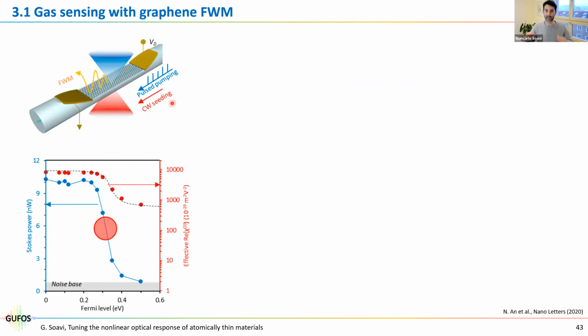So now we take a fiber, we remove the top part, and we make what we call a D-shaped fiber. By doing that, we will be very close to the core of the fiber. We now place graphene on top of it in a way that light that propagates inside the fiber will have a very strong interaction with our graphene flake or graphene device.